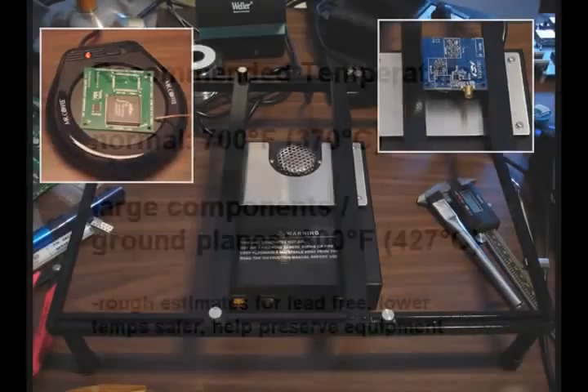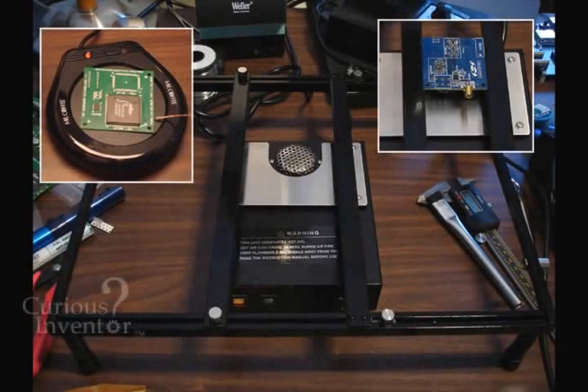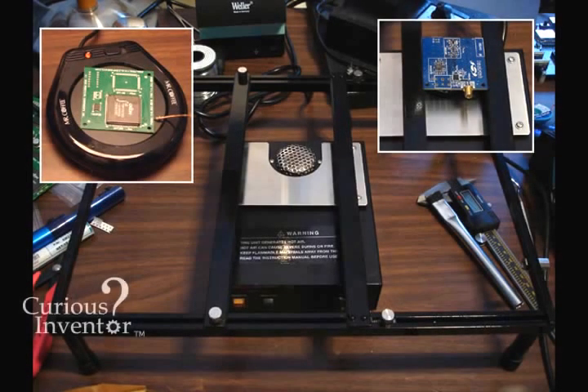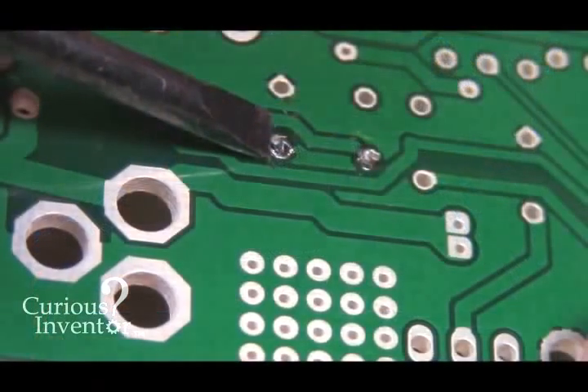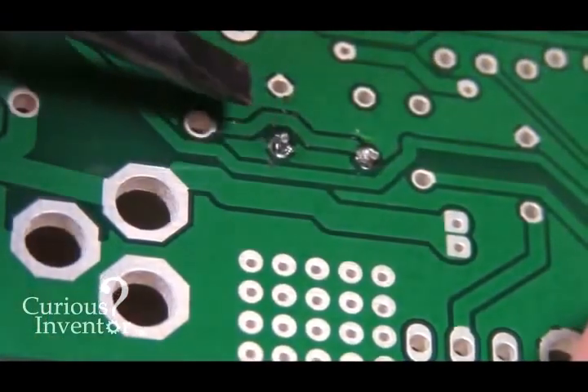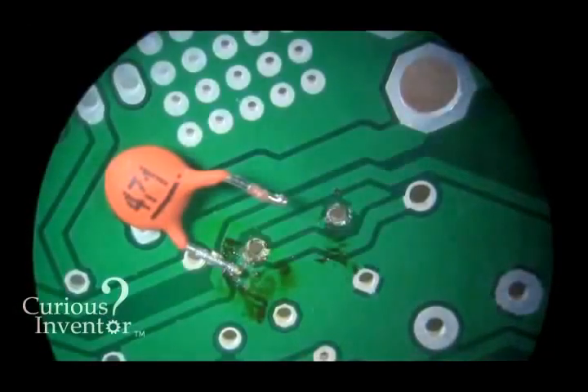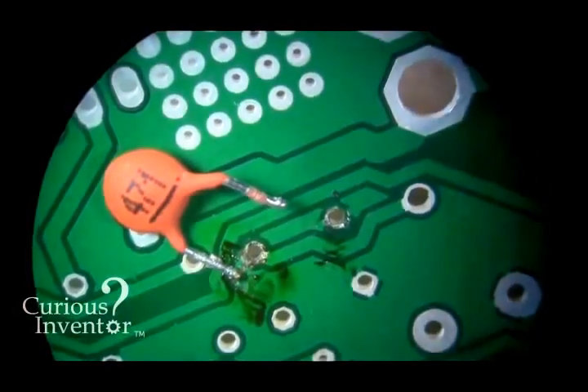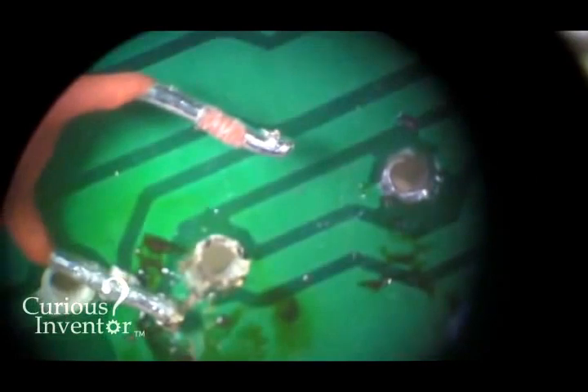For cases with large ground planes or boards with 4 or more layers, a preheater can be used with a stand like this to warm the entire board before applying heat with an iron. Another difficult condition results from poor quality boards. On this particular board, almost any amount of force used to break the remaining solder connection after wicking will damage the plating on the through-hole.